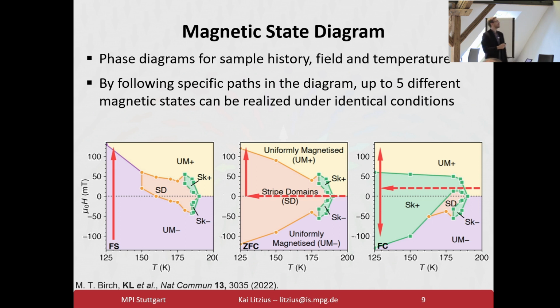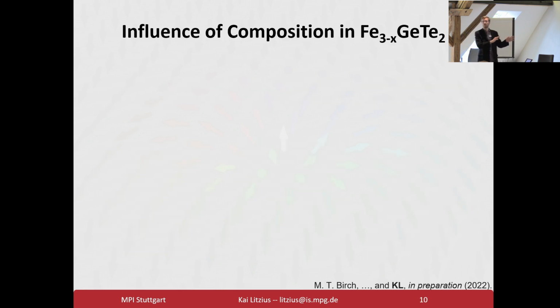Okay. So in this case, you end up with a skyrmion state, and that means that depending on the history, you can achieve up to 5 different magnetic states, completely different configurations under identical conditions. So for example, we can freely select between a stripe or a mixed state or a skyrmion state. So that's essentially the history dependence. Now let's talk about the dependence on composition, what the composition of the van der Waals system does to the system.